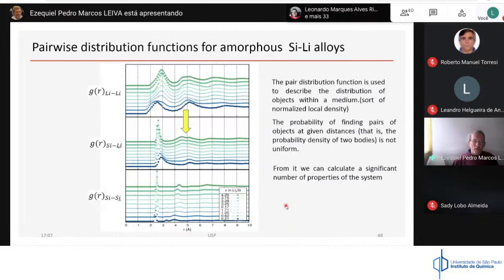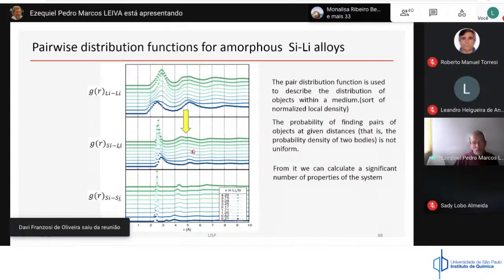The other thing that you can get is also the pair distribution function. The pair distribution function is some sort of normalized local density, where you can see how your atoms are distributed in the neighborhood of another atom. This is the lithium-lithium distribution. This tells you how lithium atoms are distributed relative to a central lithium atom. This is the silicon-lithium distribution function that tells you how the lithium atoms are distributed around silicon atoms, and this is the silicon-silicon distribution function. One of the interesting things we found here, and this is something we are concentrated on in our study, is the splitting of the second nearest neighbor.